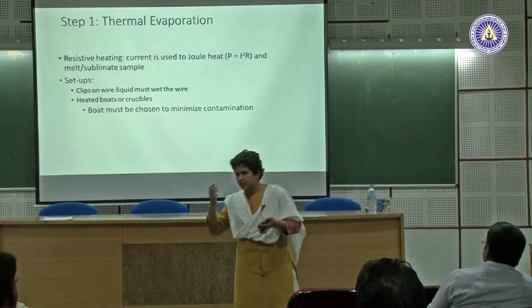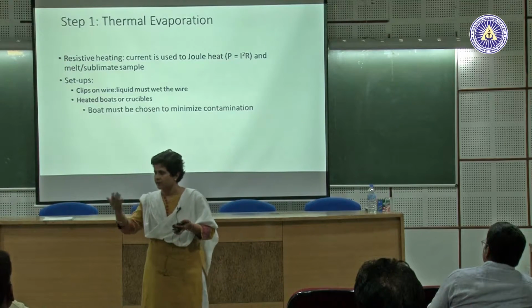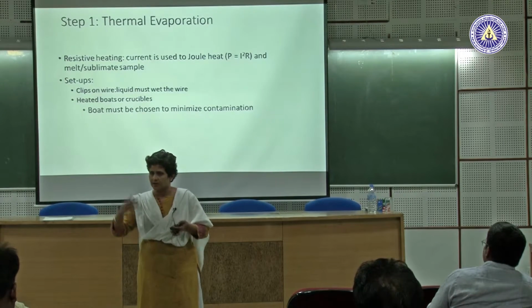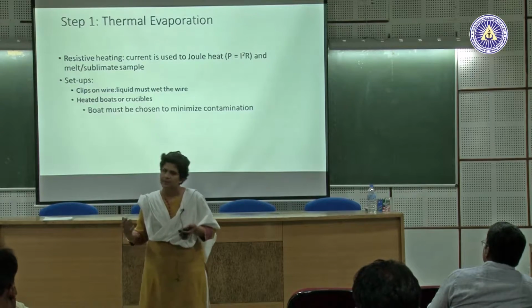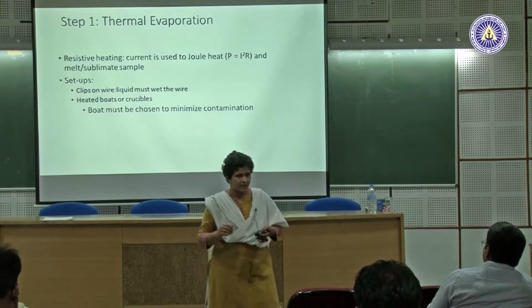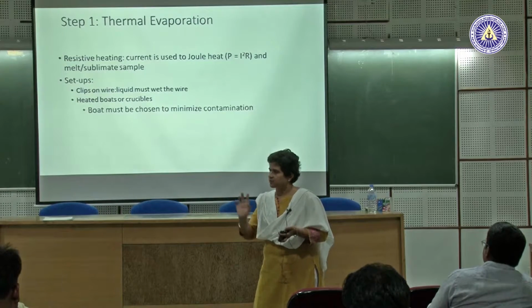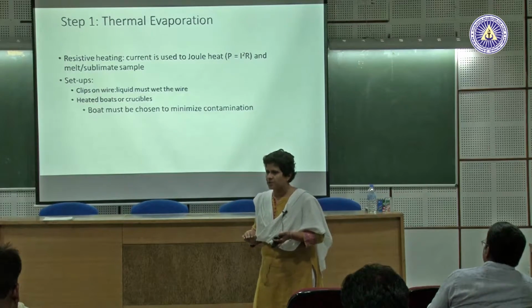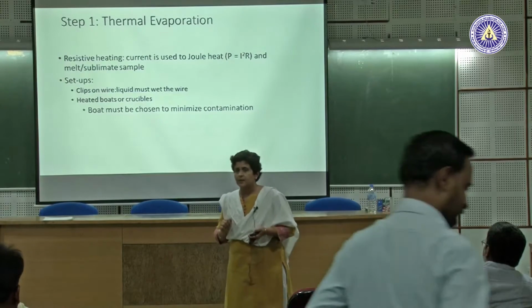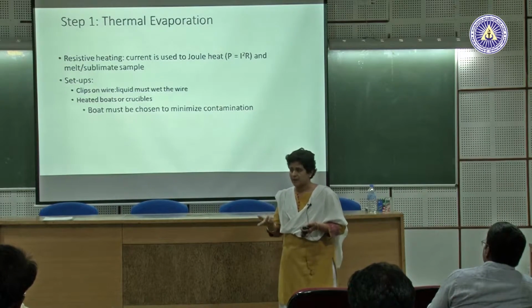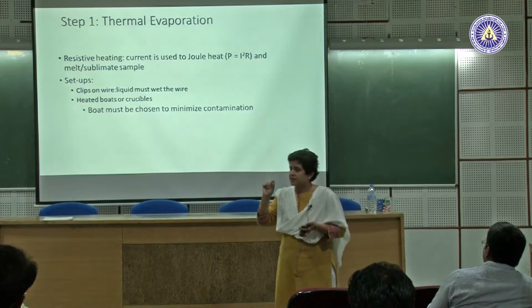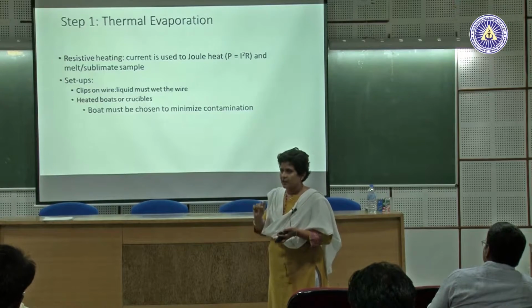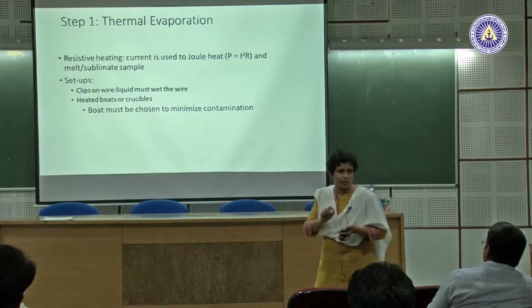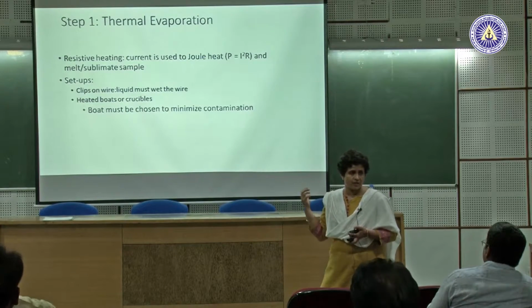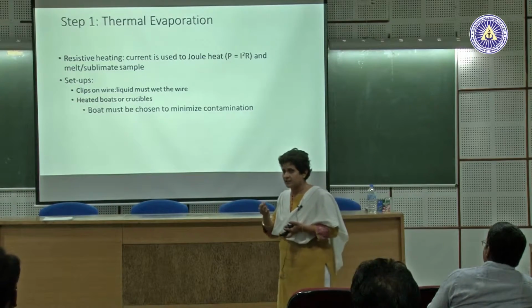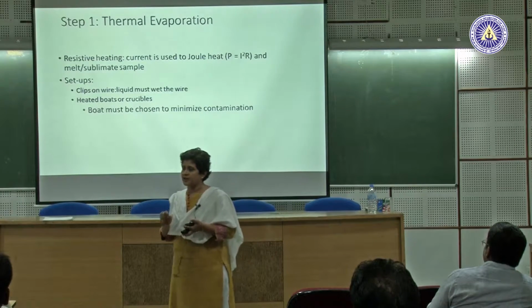Suppose a particular application I can talk about is I want a mirror finish on a glass. I just want some aluminum or silver deposited on the surface. I don't really care what the deposition rate is, as long as my final thickness is some 300, 400 nanometer, I will just deposit it. But in certain applications, especially electronics or optical applications, I want exactly, let us say, 20 angstrom. Now if I want that 20 angstrom, I must control the flux of my evaporation very, very well, and the control of it, in terms of manufacturing, is the key.